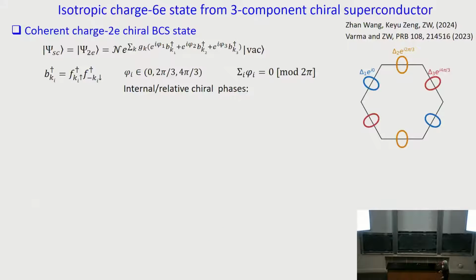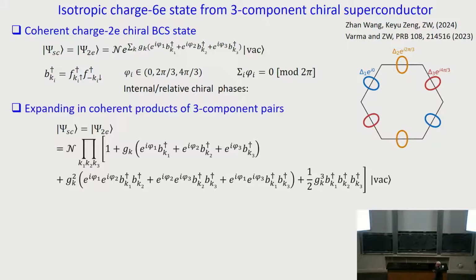I have another way of showing it. Again, an exercise for everybody to try. I can write down a charge 2e order parameter, BCS form, right? With these 3 order parameters having this phase difference. B is just a pair. Now, if you just expand this exponential, we all know how to do that. You expand, you see that I get a linear term, one pair. This term is quadratic, so it has two phases. And the cubic term has the multiplication of these three phases, and the phi's cancel out. There's no phase coupling here.